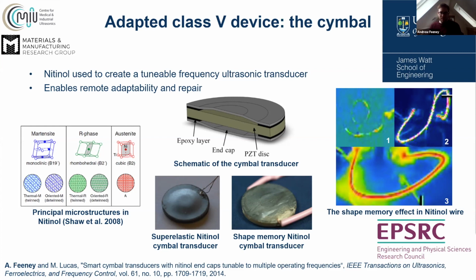One is superelasticity, and this is a reversible response to high deformation applied to it. And the other is the shape memory effect, which would be, in my mind, the basis of a self or remote repair concept. The shape memory effect is demonstrated on the right-hand side there. It would have been better with a video, I think, but these are snapshots taken from a video I took in the lab. Sub-figure 1 just shows a looped nitinol wire specimen. I then activate a current, and that current starts to change the microstructure of the wire, and it tries to recover its original configuration. That's what's happening in number 2. And then in number 3, after it's transformed, it's reached its original configuration. That's the underlying concept of using something like the shape memory effect.